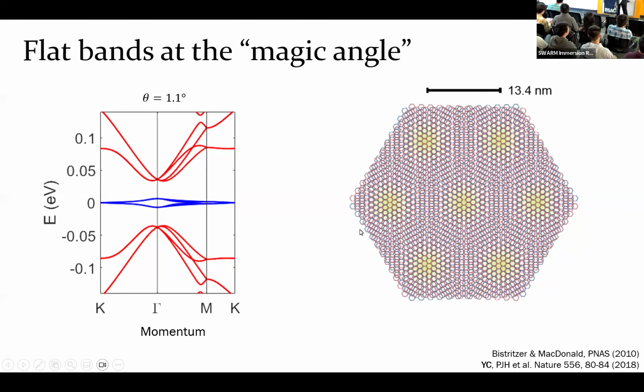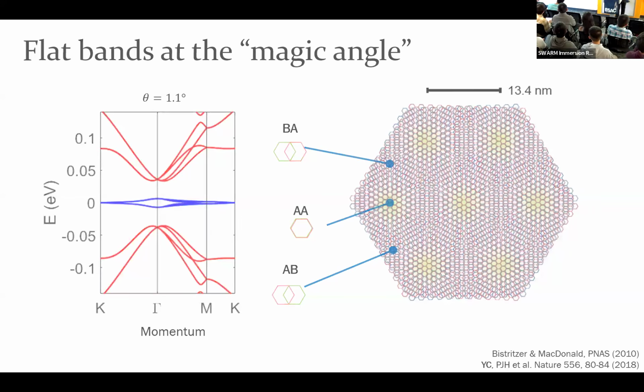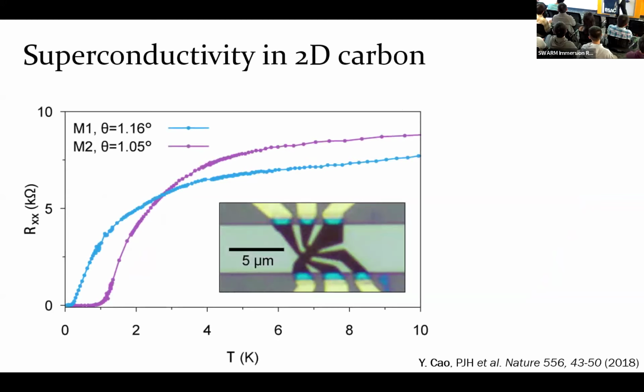And if you do some numerical simulations, you find that they're actually getting almost stuck at this so-called AA spot, the brighter spots in these Moiré patterns. And when the electrons behave like they're stuck in real space, then they behave fundamentally differently. And as a result, we're seeing these really intriguing phenomena, including superconductivity, which is a state with zero electrical resistance.